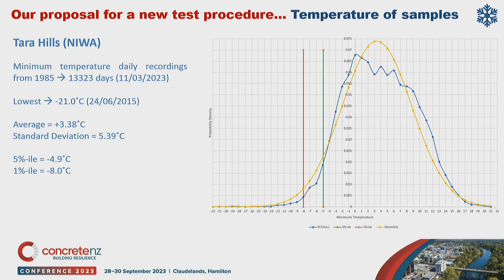The yellow curve that you see is the normal distribution coming from the original data, which is the blue curve with the recordings. And the yellow is the normal distribution starting from the average and the standard deviation of the original data. So it resembles decently a normal distribution. The only thing is that for temperatures below minus 4, the yellow curve is a little bit higher, so there is a higher probability density for the theoretical normal distribution.